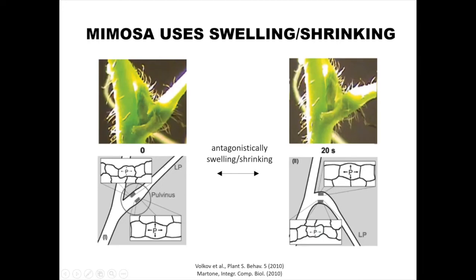So when the upper layer is shrinking and the lower layer is expanded, so the water pressure is changed between those two, you have this motion upwards. And if the water pressure in the top layer is increased and in the lower layer is decreased, you have this downward movement. So you see that it's purely osmotic pressure within the cell layers, and you can also see it takes about 20 seconds to change the water pressure in the adjacent cell layers and do this movement.